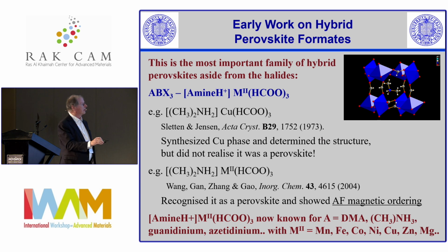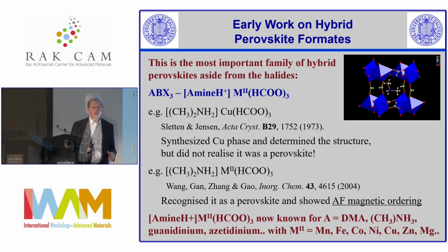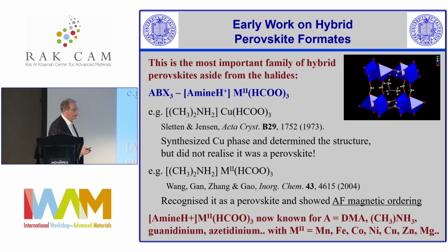It wasn't until Song Gao essentially reproduced what these people had done that he realized that it was a perovskite, which is very important. And secondly, he showed that these materials can undergo antiferromagnetic order when the B cation is a transition metal. And so what's happened over recent years is that you can have all sorts of different amines, not just dimethylammonium and methylammonium, but things like guanidinium, azetidinium, formamidinium, and other things you can't even pronounce. And then in combination with many of the first row transition metals plus magnesium and one or two others, this is actually quite a broad platform.